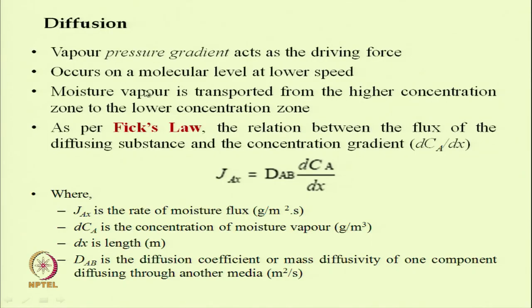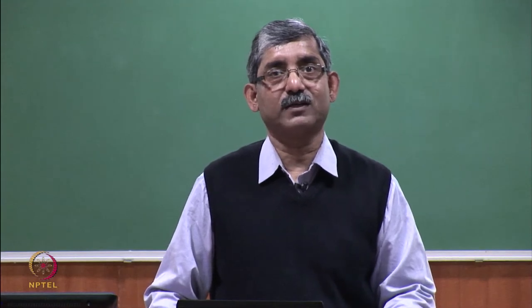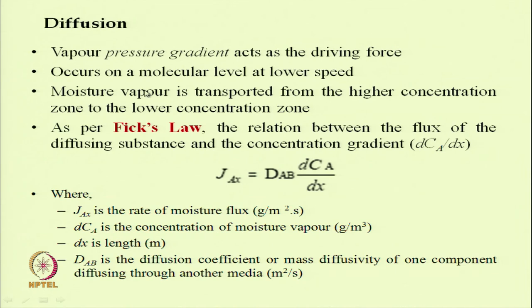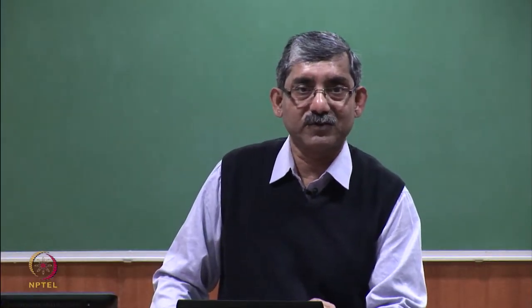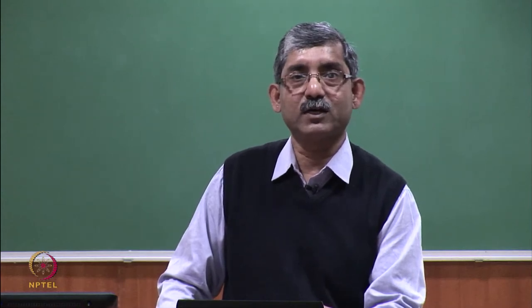In diffusion, the vapor pressure gradient is the actual driving force, and diffusion takes place by Fick's law. This diffusion occurs on a molecular level at low speed, so always diffusion takes place at lower speed. If there is any air turbulence, then there will be forced convection. As I have mentioned, moisture vapor is transported from a higher concentration to a lower concentration zone, and here the concentration gradient dCA is the driving force, dx is the length transmitted, in this case the thickness of the material, and dAB is the diffusion coefficient.